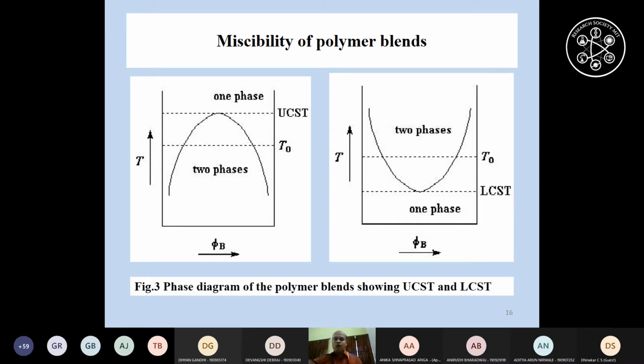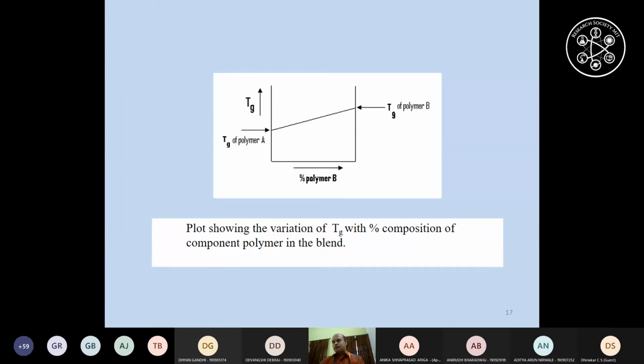So you have to find out at what ratio you are going to get miscibility of your polymer solutions. That is called one phase, or two phases meaning phase separation. In the miscible region, if you prepare your polymer blends, they might have good strength, and you can go for whatever applications you are thinking of. If there is already phase separation between the two polymers, then we can't go for any applications. So we have to identify this using chemical engineering calculations. Of course, nowadays modern research is all instrument based, not classical methods.